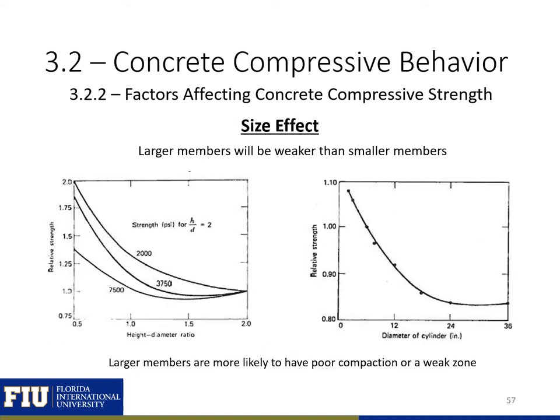The size of concrete members will also impact the strength. The two plots shown here show the relative strength plotted versus the size of an unreinforced concrete specimen. Larger members will generally be weaker than smaller members, because larger members are more likely to have poor compaction or some other type of weak zone. Note that this size effect can be mitigated with the proper use of reinforcement.